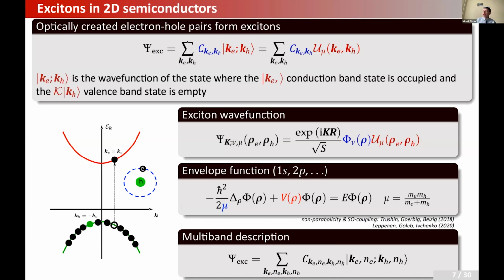So if you use this approximation, and if furthermore you consider the Bloch amplitudes only in the vicinity of the band extrema, then you can transform this problem back to the very simple effective mass problem for the wave function of the exciton, which in real space is presented as a product of the two-particle Bloch function. This function really knows from which bands the excitons are formed, and it is extremely important for optical properties, for selection rules, and also for the fine structure.